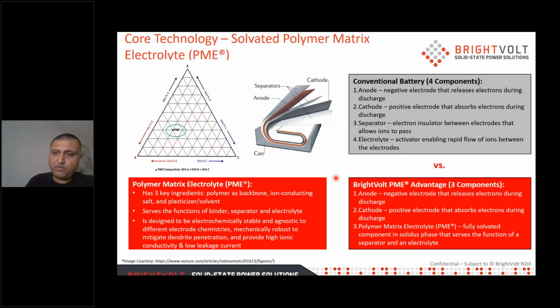And after you mix that and prepare your slurry, you would proceed to prep your electrodes just the way you normally would in terms of coating them onto a substrate and then going through drying and calendering and so on. And at the end of that step, we put one more layer of our PME on top and then allow that PME solution to fully dry or solidify. And so the benefit of doing that is once the electrodes are prepared through that process, you really have just 2 electrodes, your anode and your cathode, that you can slap together, essentially making a battery. So it's something as simple as slapping 2 slices of bread and making a sandwich.